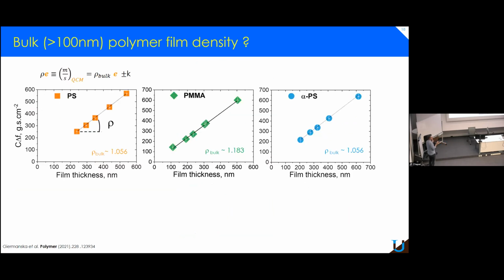So before going to small thickness, we checked that our approach was okay for a thick layer. We were actually able to retrieve the bulk density of the film that we were spin coating on the QCM sensor: PS, PMMA, and alpha-methyl polystyrene. With this QCM approach, we were able to basically get back to the real density of the polymer in bulk. So we were quite happy with this result.